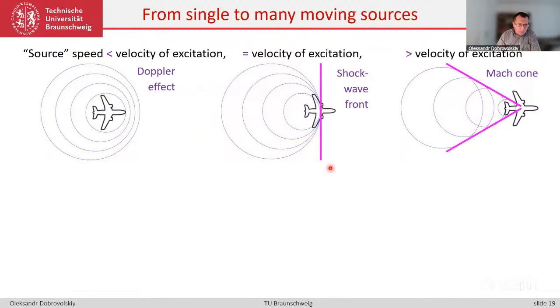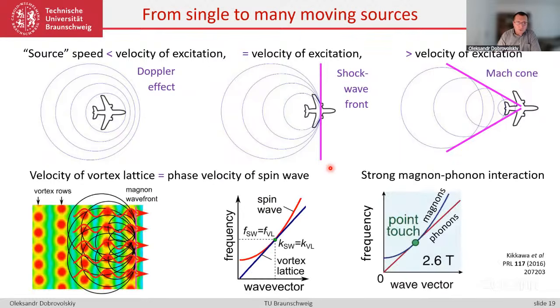So basically, for vortices in superconductors, obviously we have many sources. And then this self-synchronization condition is very important in order to preserve the long-range order of the moving vortex lattice. As illustrated on the left-hand side, even if there are deviations in the periodic arrangement of vortices, the generation of spin waves acts back on the vortices, and by inducing eddy currents, the vortices are adjusted to form straight rows, moving in phase, and this leads to a kind of resonance-enhanced interaction with the generated spin wave.